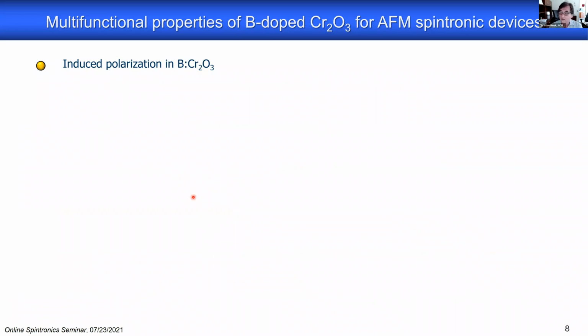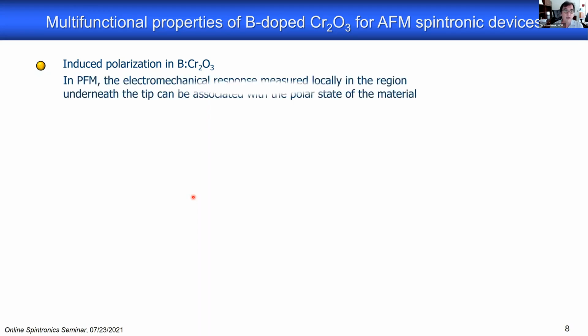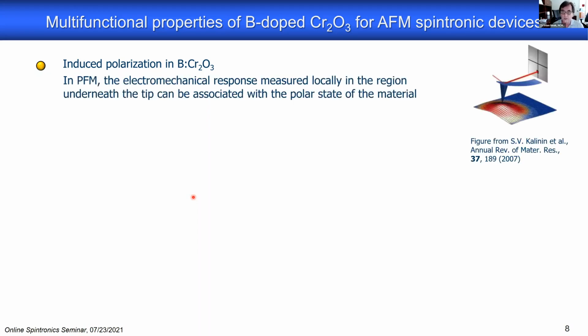But before I go there, and this is not historic, but I put it now into this context of new effects from boron doping. Another effect that comes with the boron doping, fully surprisingly, is induced polarization. And this is a collaborative approach together with Alexei Gruverman, also from the University of Nebraska-Lincoln. He uses, among other scanning probe microscopy techniques, piezo force microscopy, which is a version of atomic force microscopy that is sensitive to the mechanical displacement of material due to a piezoelectric effect.